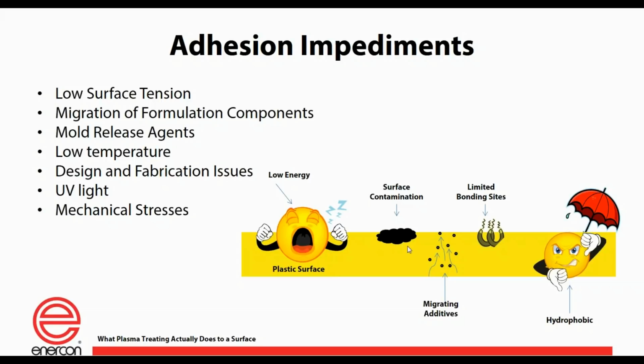Another problem we run into is migrating additives. If you're putting flame retardants or some other additive into, say, your plastics, those can be limiting factors to adhesion. Recently, I heard that there's some changes in the plastics being used for wire and cable because of some larger delta T, or delta temperature, that these wire and cables are seeing when they're on ships heading around the country and around the world. So they're having to add more additives to this, and this is changing the profile of their material and their surface. All of these give you limiting bonding sites and make a very hydrophobic surface.